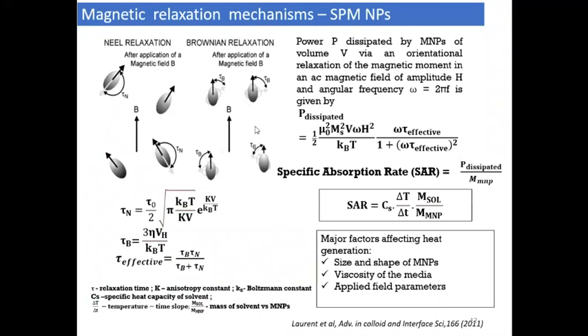So this is due to physical rotation of the particles, and this is due to the spin rotation of the particles. And we see that the Néel relaxation, due to the moment developed, depends on several factors. So these factors are generally KV, where K is the anisotropy constant, and V is the volume of the particles. And the Brownian relaxation depends on eta, the viscosity of the fluid, and the hydrodynamic size of the particles. And there is effective relaxation, and the effective relaxation is 1 divided by tau_eff equals 1 divided by tau_B plus 1 divided by tau_N. And if you do this, the effective relaxation time can be written as tau_B tau_N divided by tau_B plus tau_N.